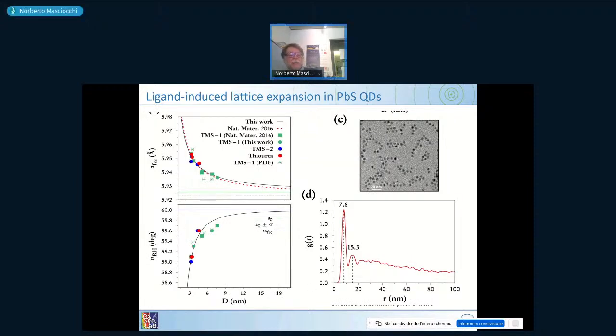The plot you see up there is the same plot seen before after we collected data at a synchrotron, same condition, from preparations done with different methods in different laboratories by different people. And you can see that if you forget the starred ones, which are obtained in a completely different manner, by the PDF way, but not by the Debye scattering function, so forget about the green stars, everything else falls more or less on the same line. The original line is the dashed red one. Once introducing more data than the 3 which we had before, then these all align on the same trend and a much better definition of the trend is obtained.